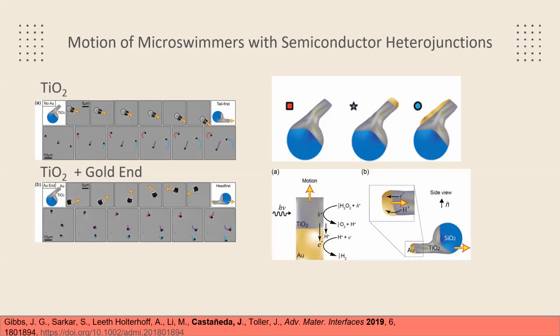So why is this? The titanium interacting with that gold, there's an electron transfer going on with this semiconductor heterojunction on my microparticles. So the electron hole pair that's forming on the titanium dioxide, the electron is jumping to the gold and then forming its own redox reaction and causing that microparticle to switch directions.